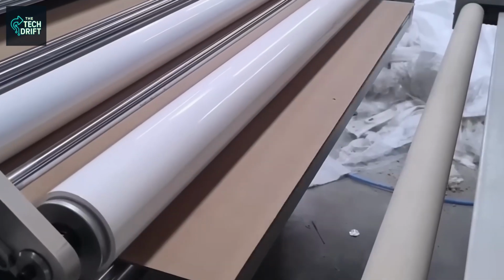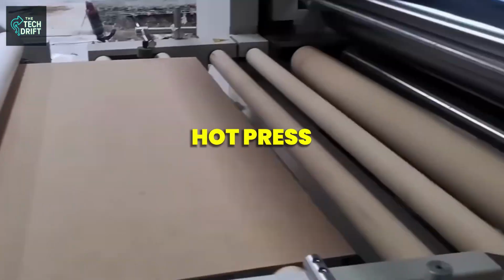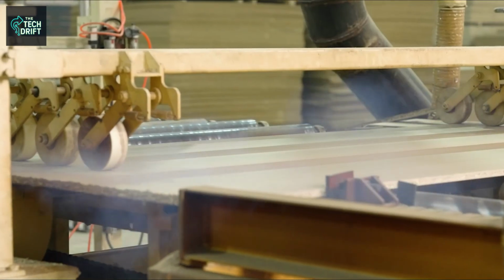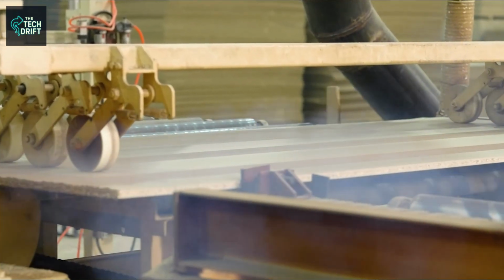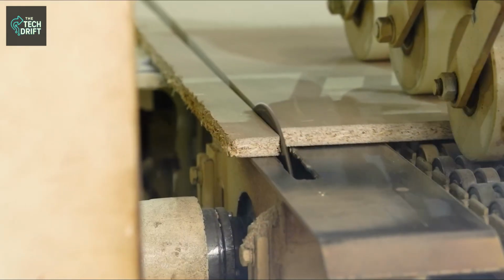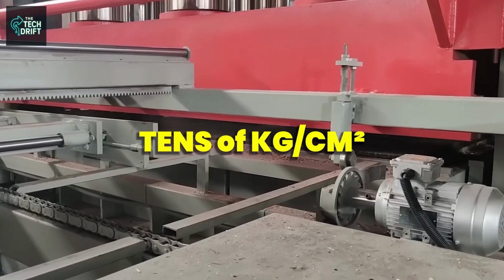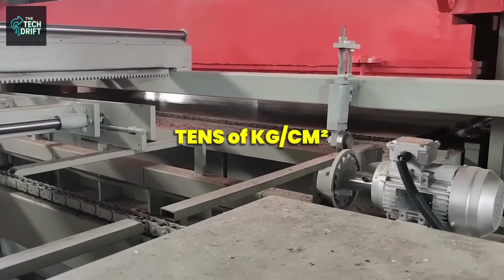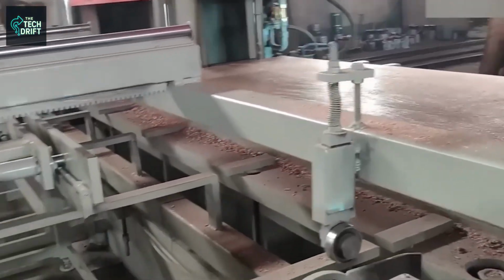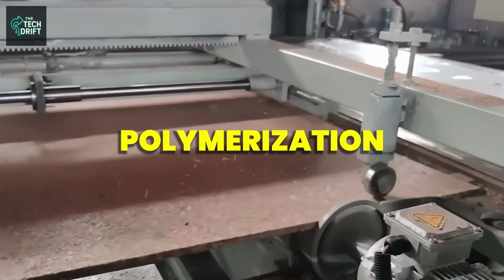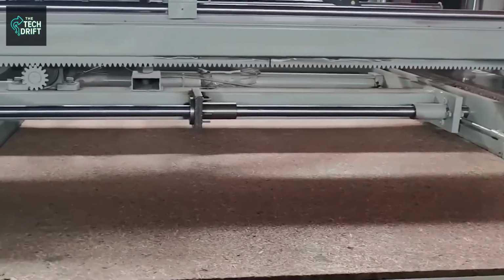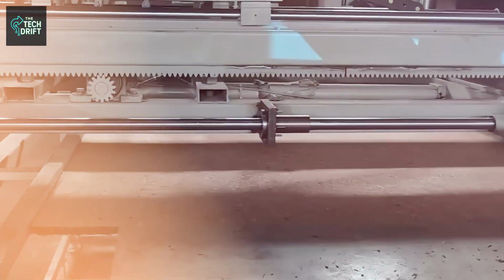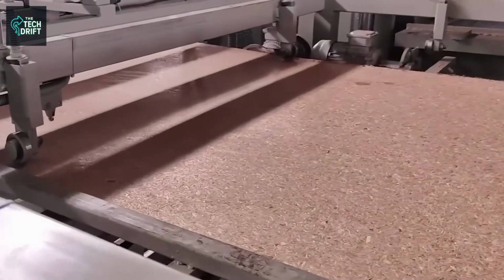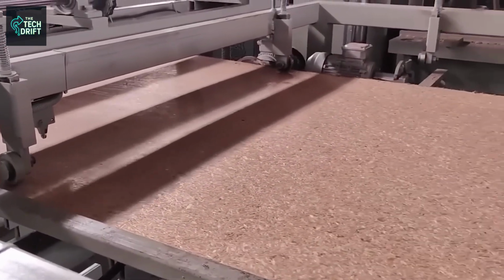Then comes the most powerful moment of the process, the hot press. In this enormous press, temperatures rise to around 400 degrees Fahrenheit, while pressure builds up to tens of kilograms per square centimeter. Under this intense heat and force, the resin undergoes polymerization, where it hardens into a permanent, rock-solid bond. In just a few minutes, the loose, fragile mat is transformed into a dense, monolithic board with incredible structural integrity.